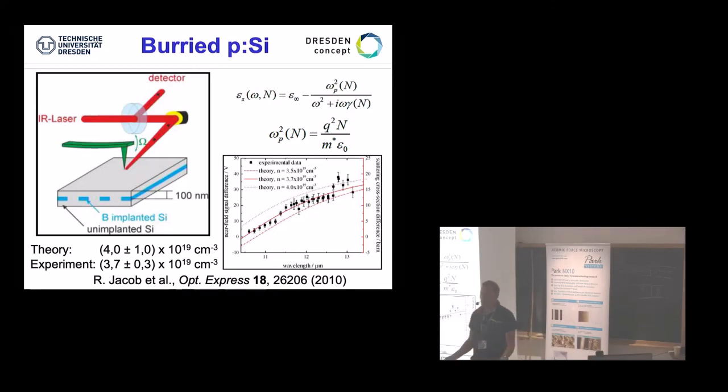So in a physical model, what you could say is, this is like a good sandwich. That means we have something which is really tasty, which is the boron. Well, how can we figure that there's boron there? Well, what we do is we just apply a very simple model, saying we don't know what it is. Well, it could be electronic, meaning that it has electrons that we can excite. It could be phononic, meaning it has phonon resonances which are different from the surrounding, which is my silicon. So we need to sweep through the whole wavelength range in order to really hit somewhere some kind of resonance.